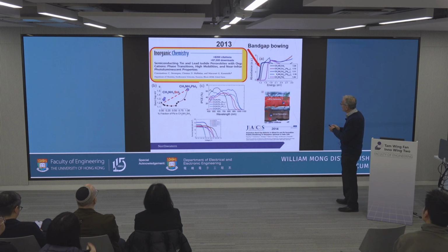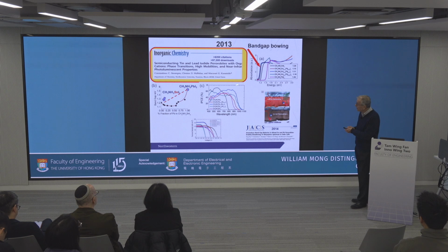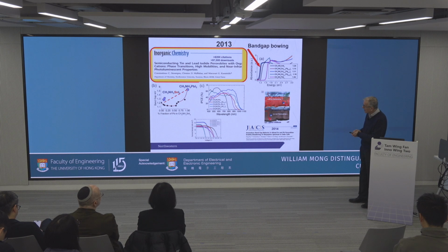Also, in this same paper, we also discovered and published something else which became important later. And that is the band gaps. These are, again, the absorptions, and these are the band gaps. And what we have here is tin band gap, which is black. The tin band gap is lower than the lead band gap in methylammonium, as you can see here. But when you mix lead and tin, the mixed ones are even lower than the tin. So now you have even lower band gap. We demonstrated that this can actually be used in solar cells, so you can capture more light in the infrared. And this is our paper in 2014, showing that when you have mixed lead and tin, you can push the absorption into these numbers in the infrared.